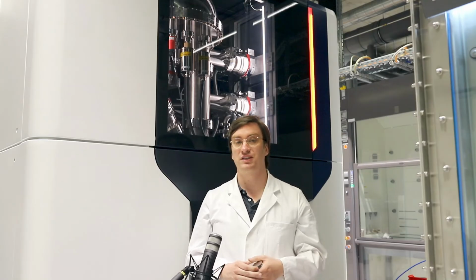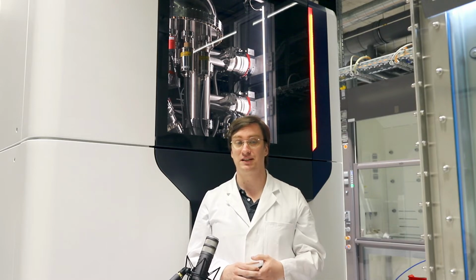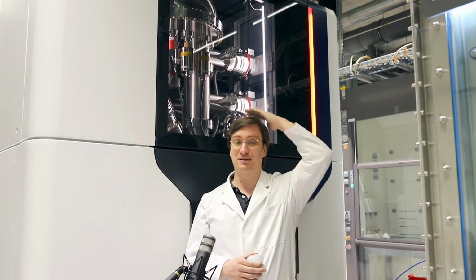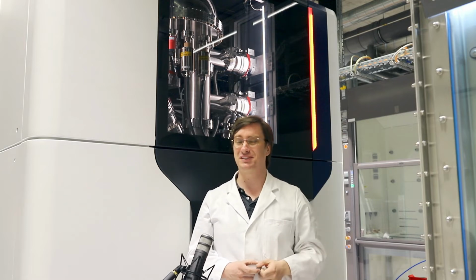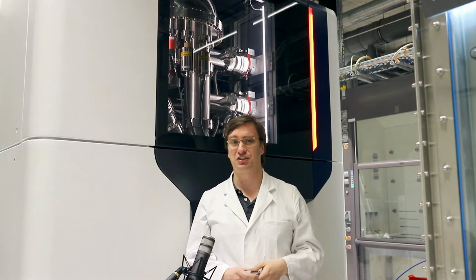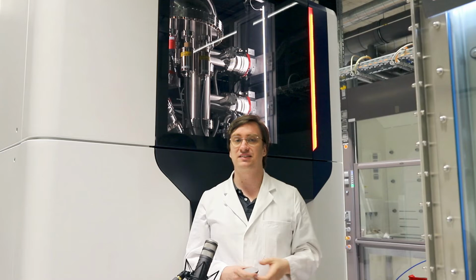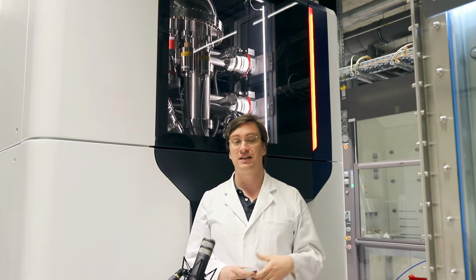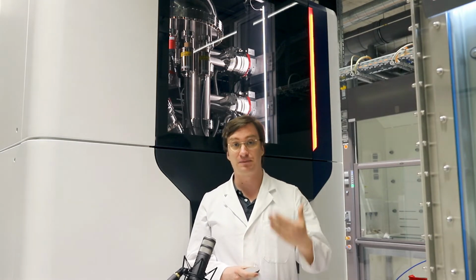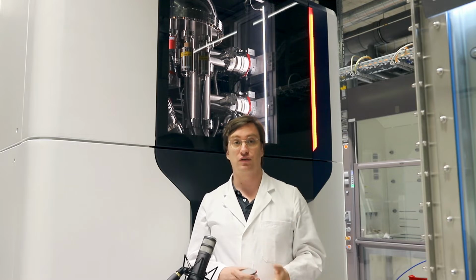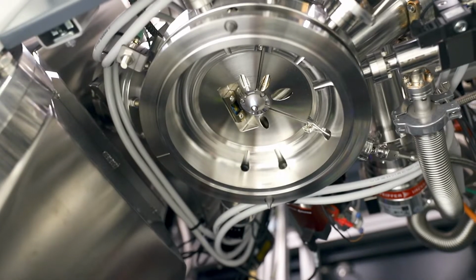So behind me, you see our XPS. Our XPS is a little special, and as you can maybe tell by the height of my head, I'm not a very small person, this is fairly large. Why is this so large? Well, this is a near ambient pressure XPS. That means we can measure XPS at pressures of up to 100 millibar.